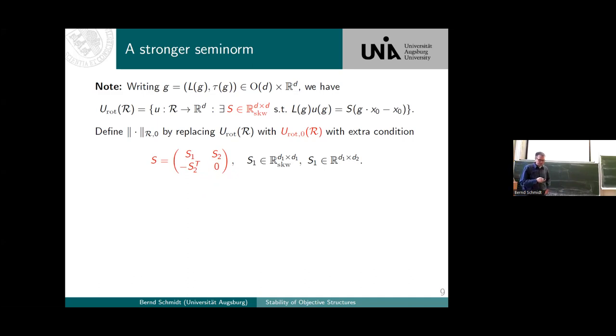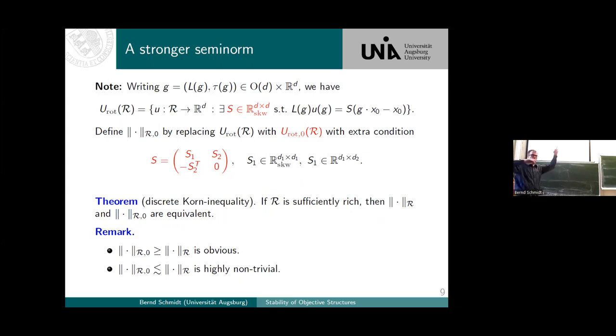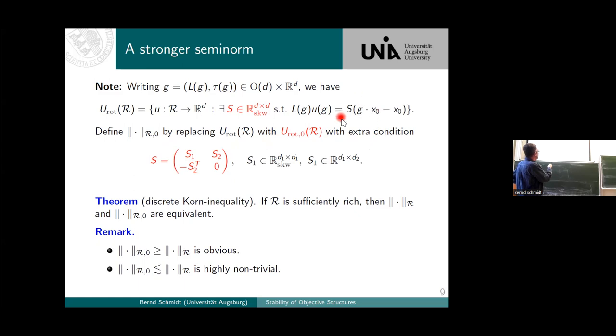One of the first main theorems is the following: these norms are equivalent, provided the test set is sufficiently rich. For space groups that invade the whole space, the upper parts aren't there at all, S needs to be zero, and this becomes a full Korn inequality. The previous semi-norm allowed a different S from site to site; now with this view, S is equal to zero everywhere for the space group — so this is a full Korn inequality.